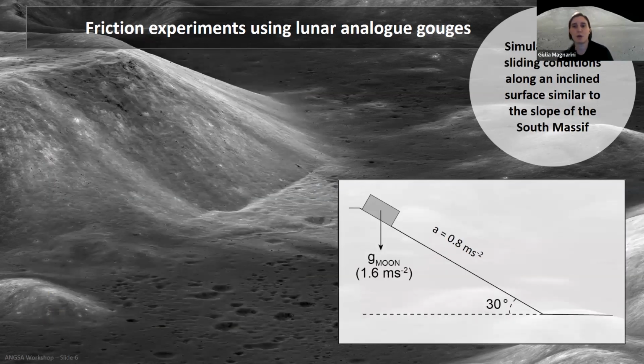So we tried to simulate the sliding condition along an inclined surface similar to the slope of the South Massif. And so the acceleration we have here, 0.8 meters per square second, was the minimum acceleration we could apply to our rotary column. And so this is giving us a 30 degree slope, which is an overestimation of the current slope of the South Massif. Next slide, please.